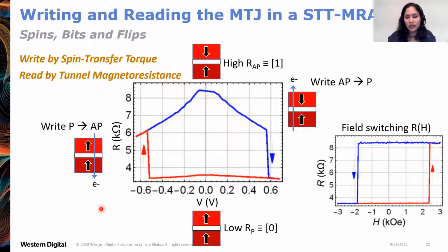So by spin transfer torque, this is how you can operate this magnetic tunnel junction by using a current or applied voltage and without a magnetic field. So here's how this works. This is resistance versus voltage. And we can start here at the high resistance state, for example, a written bit of 1, when the two ferromagnets have their magnetization anti-parallel to each other. And you can read this at low voltage.